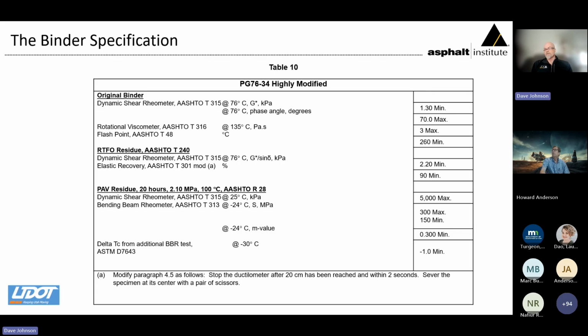Anything else, Howard, you want to say about that before we move on? No, I mean, just to emphasize that a 58-28 looks like it's going to be the best for cracking because it looks so soft, but actually it's the worst. And you can see that in the elastic recovery. We could see it in the M values, but a picture is worth 1,000 words, and showing a video of it makes it a lot easier for people to see the difference. That just the high mod is stronger. It's not brittle. Yeah, it shrugged it off, much like it's doing out in the field in the various installation locations.